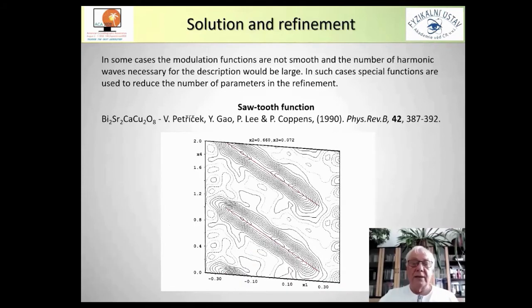Another specific function was used for bismuth superconductor 2212, where the oxygen atom was almost linearly modulated with some discontinuity. With this special sawtooth function, the number of parameters was considerably reduced and the structure was correctly described.